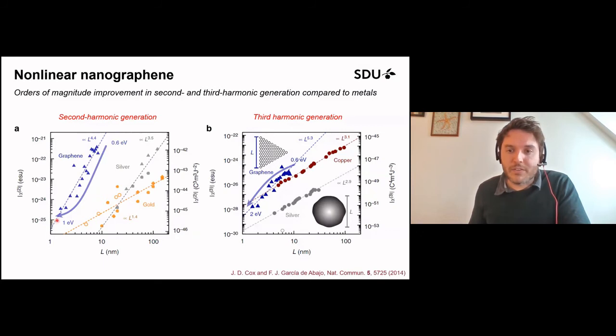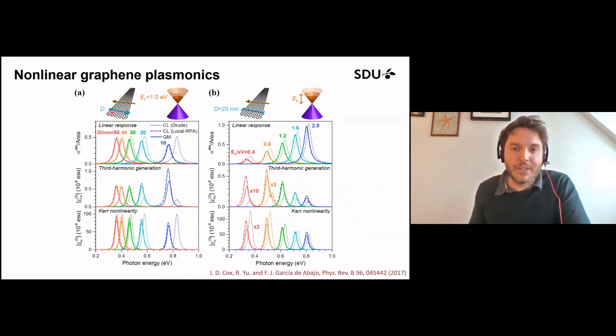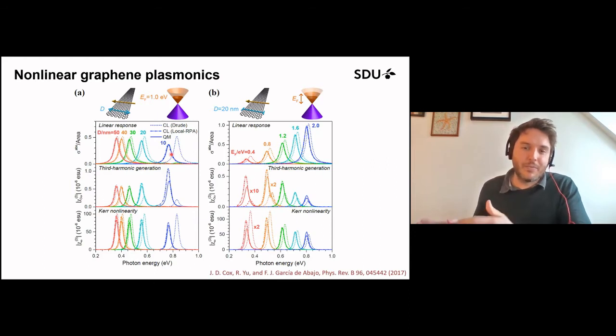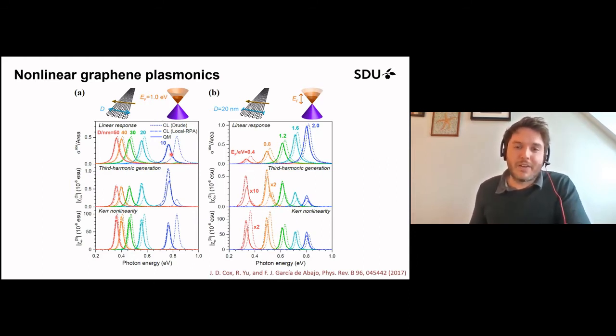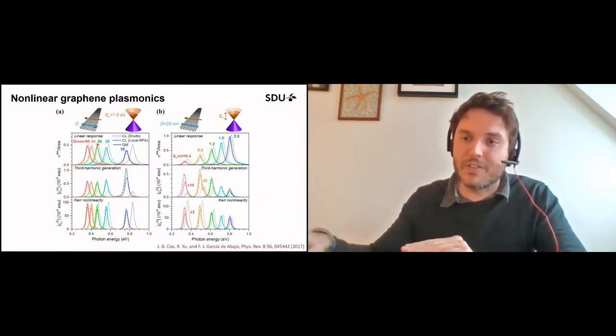Here we find already that second and third harmonic generation in graphene compared to these conventional particles, just predicted in theory of course, is orders of magnitude higher, and this definitely warrants further experimental investigation in these systems. Also for graphene nanoribbons, we see dramatic optical nonlinearities. We have these nonlinear susceptibilities that are very high. The numbers are probably meaningless to most of you, but these are actually very good numbers. So it means that graphene should be able to enhance the nonlinear optical response dramatically, particularly when you excite the plasmons. And then we've also been interested in the quantum finite size effects that you might run into when you get to very small sizes for your structures. But typically when you're above 10 nanometers or so, 20, 30 nanometers, you can already go to a simpler model that treats the graphene as a homogeneous 2D structure.